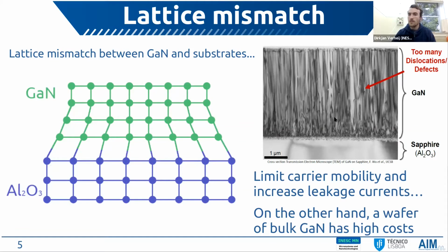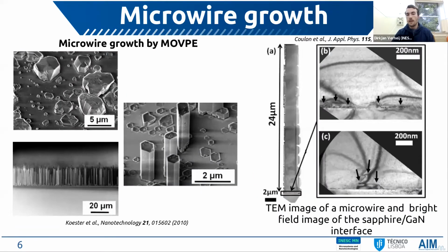So here in this transmission electron microscopy image, we can see all these black lines, and these black lines are all dislocation defects. These dislocations then limit the carrier mobility and also increase leakage currents, which is obviously not a desired property when creating devices. This could be overcome by growing very thick films of gallium nitride, but this has the downside of very high costs. So we opted not to use thick films or bulk gallium nitride, but to invest in microwires